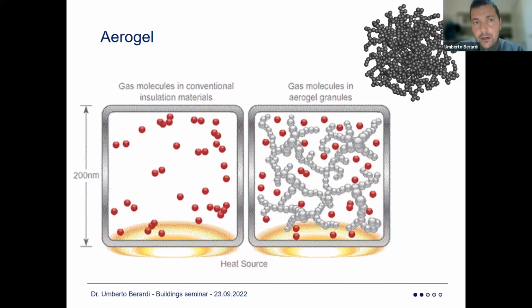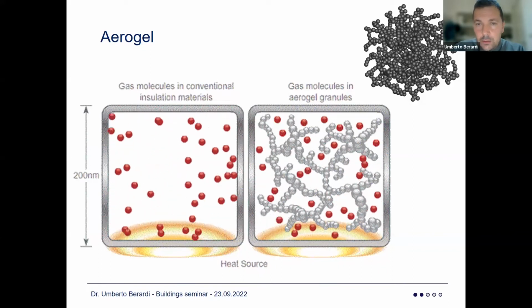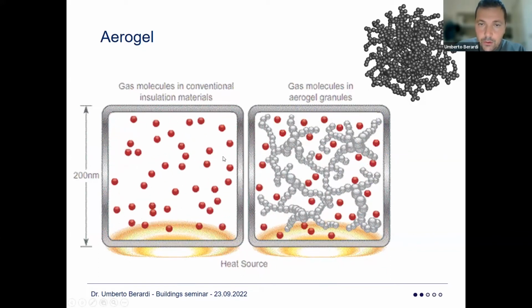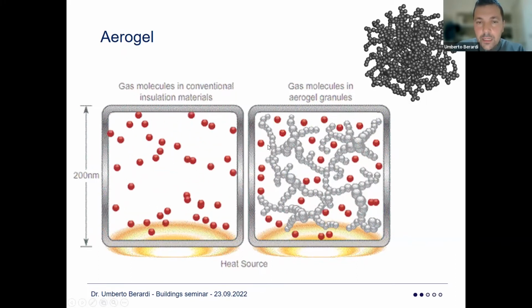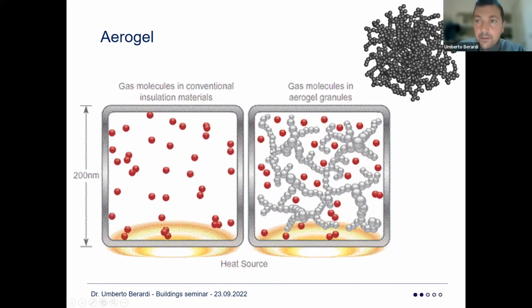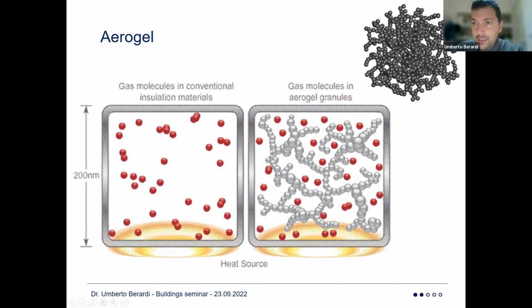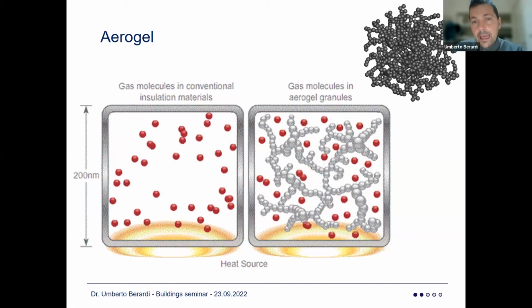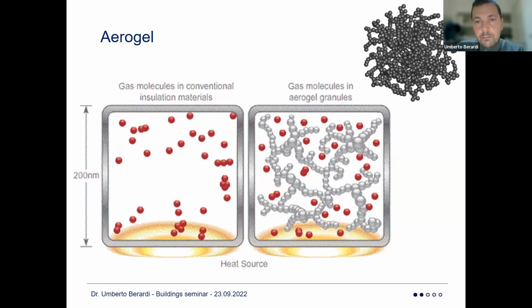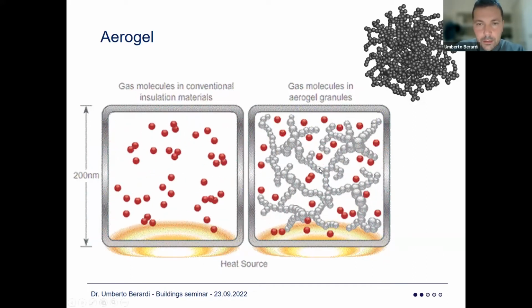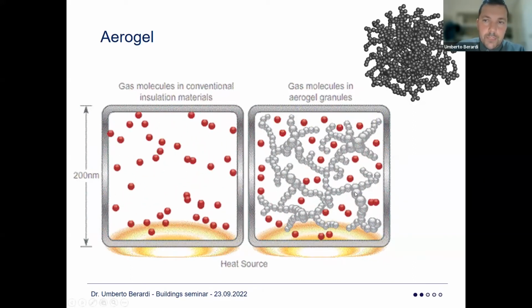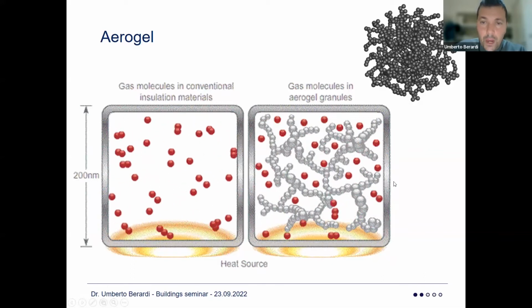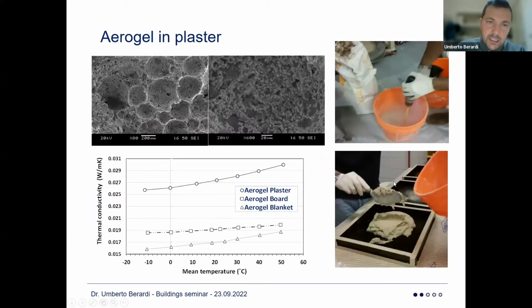So in brief, aerogel does not really enhance conduction because the structure is like a pearl chain. They don't really have convection because particles never touch each other. They never really move over significant space at the micro scale, and they don't have a lot of radiation because they put an opacifier in the structure. So in brief, from a thermodynamics point of view, these are great ways to lower the thermal conductivity of materials.